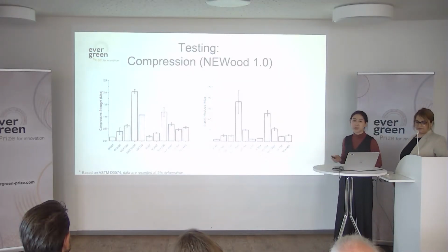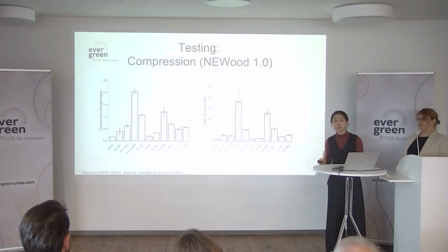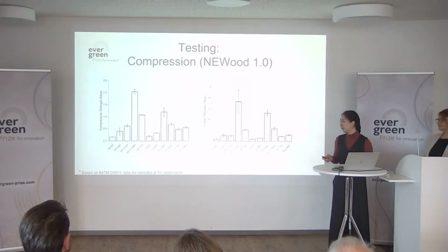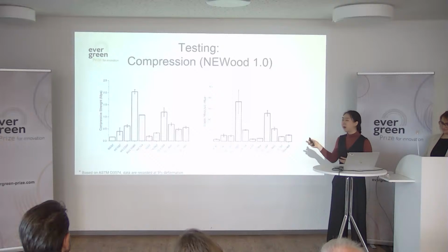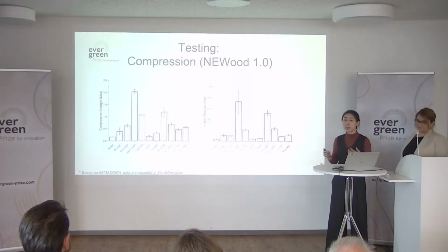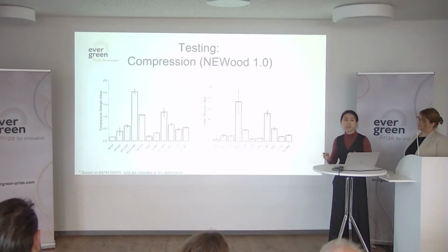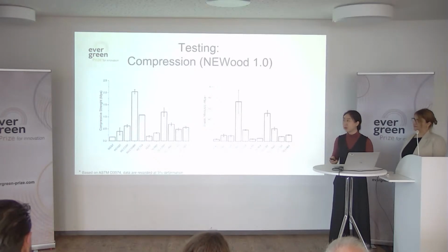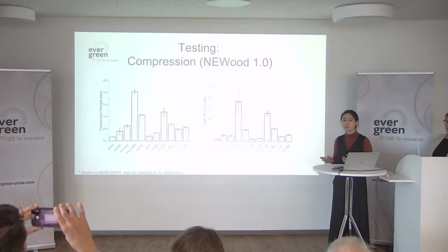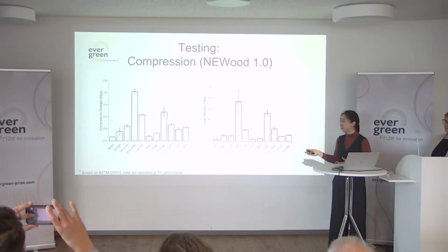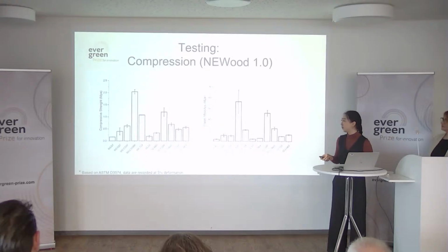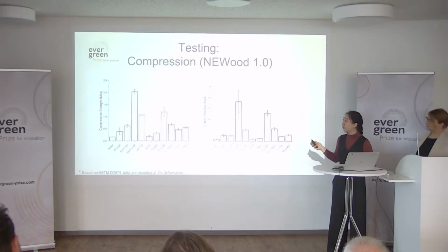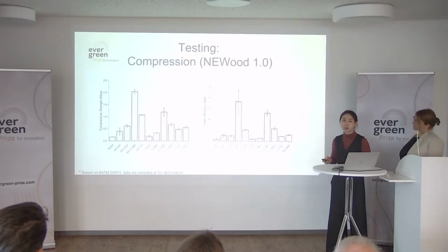In this set of tests, we actually tried to use different substrates of different particle sizes, and we used a combination of them. What we found from this is that when we mix different substrates, it actually helps the mycelium grow better and denser, and that actually creates stronger materials. This is because the mixture of different substrates actually can help the mycelium grow due to the different types of nutrition for the mycelium within the substrate itself. That was very interesting. And with that, we were able to achieve compressive strengths of up to 2 megapascals for our best combination.